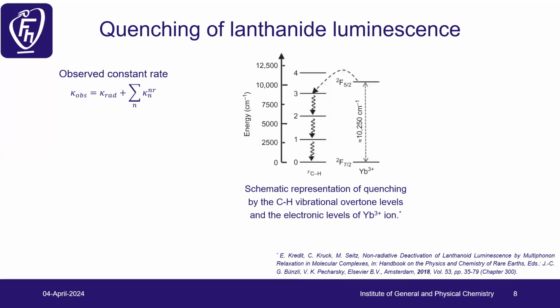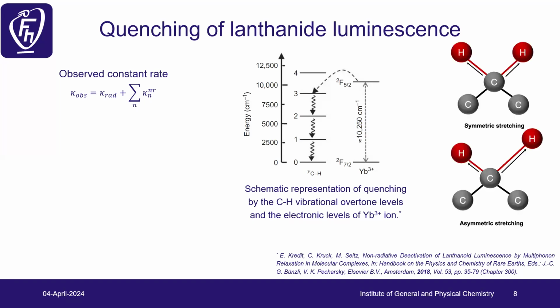Also, because lanthanides are small oscillators and forbidden, the high energy oscillators such as CH, OH, and NH groups can influence the quenching. So the lifetime that we measure, the observed one, is the radiative one plus the sum of all non-radiative relaxations that can happen. So in the case of near-infrared lanthanides, they can be easily quenched with CH and OH groups because of the second and third harmonics of the CH and OH groups.